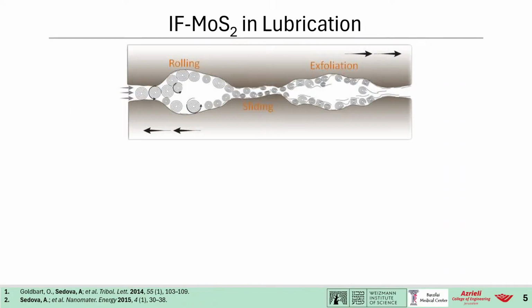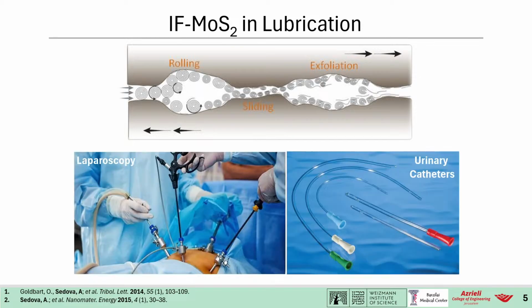So how those materials work in lubrication, we believe there are three main mechanisms: rolling, sliding. Due to their nano nature, they can go in between two surfaces with ease and serve as a separation. Due to their layered nature, they can exfoliate, and the layers will go with ease in between two surfaces. When I arrived at the lab, we wanted to study lubrication in the case of medical devices, basically lubrication between soft tissue and the laparoscope or a urinary catheter.